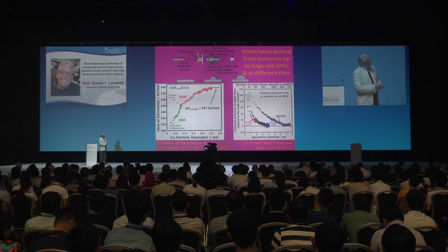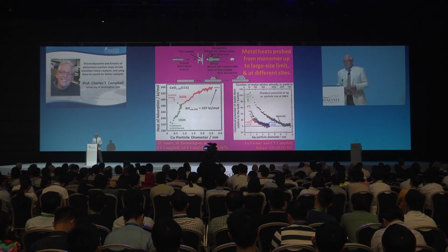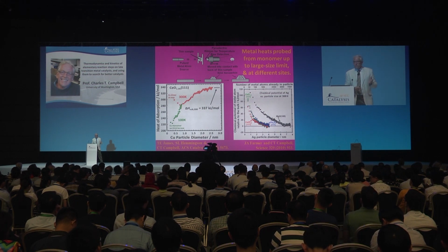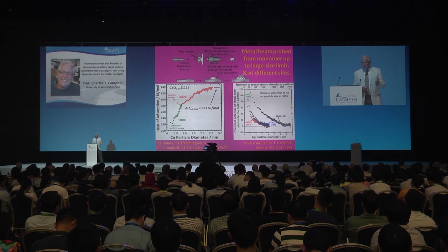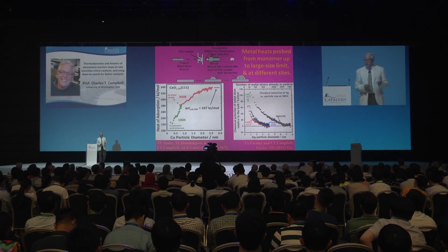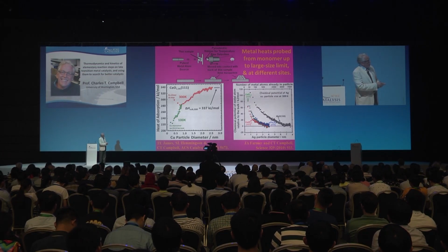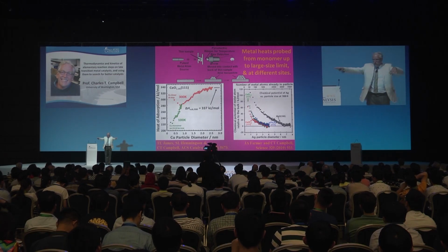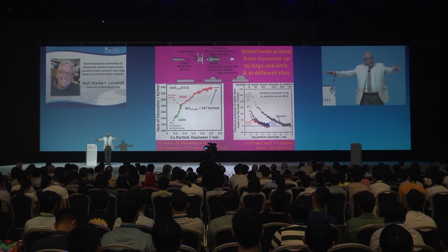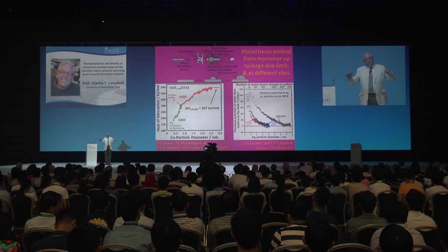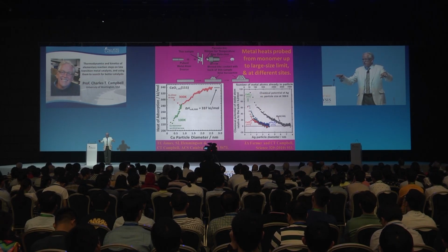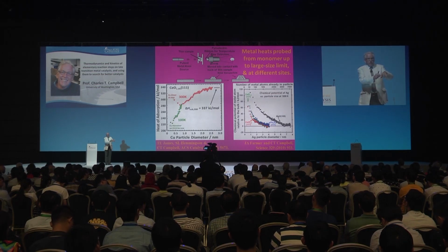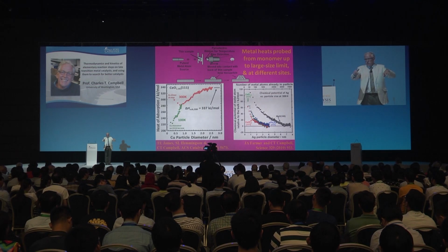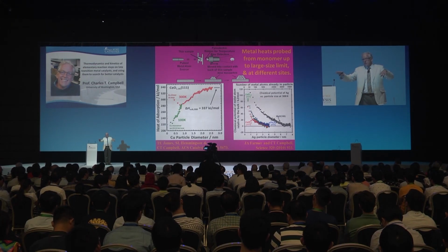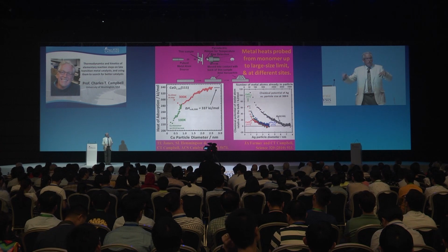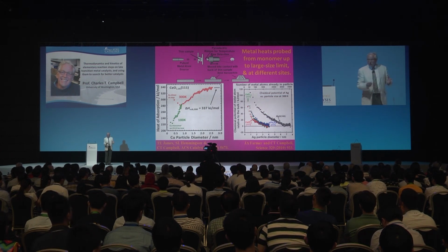And again, this decrease is related to the driving force for sintering. It turns out that if you think about the way a catalyst sinters, you have metal clusters. Sintering is when you get fewer metal clusters and they get bigger. And the way that happens usually is by Ostwald ripening, which is that metal monomers leave one particle, diffuse across the surface in a random walk. If they bump into and attach to a bigger particle, they're lower in energy, and therefore they stay there.